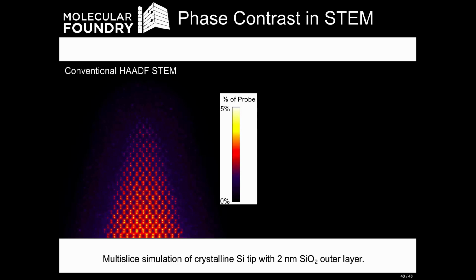But if you look at the scale bar, I'm plotting only 0 to 5% of my total probe intensity. So this conventional incoherent annular dark field STEM image is simply not very dose efficient. We're only getting contrast with about 0.5% to about 5% of our probe.